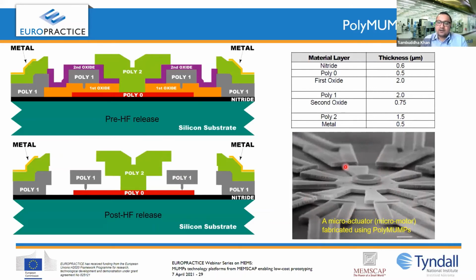There are some stators and there is a rotor part in the middle of it. The cross section of all the layers is shown here. As you can see, poly 0 is used as the anchor layer or the electrical layer, and poly 1 is used for the mechanical layer, that is the rotor, which will be suspended. Then this is the central anchor, and there are two oxide layers. They will be used for releasing the devices, that is the sacrificial layer.